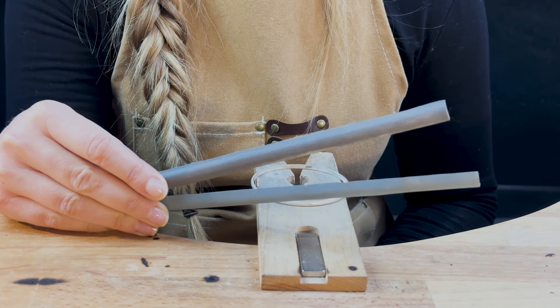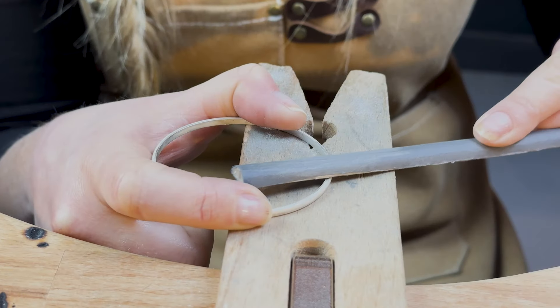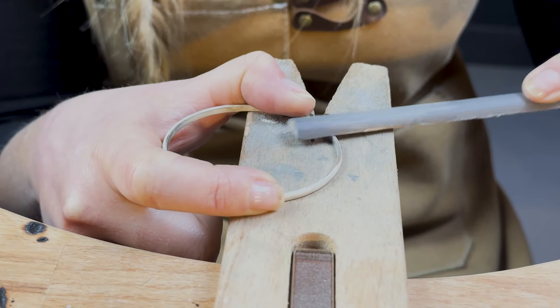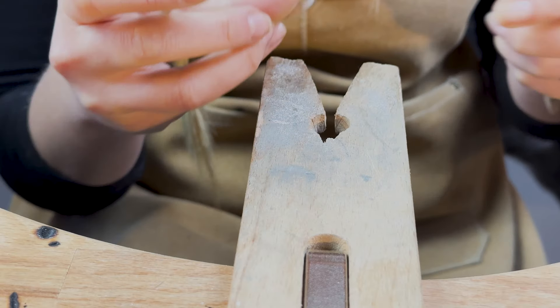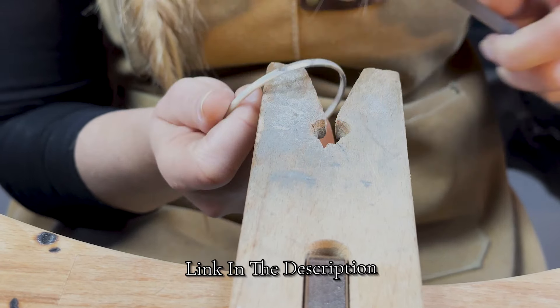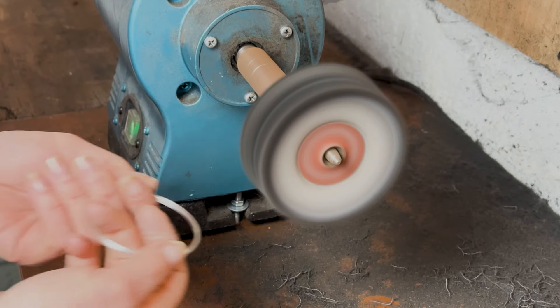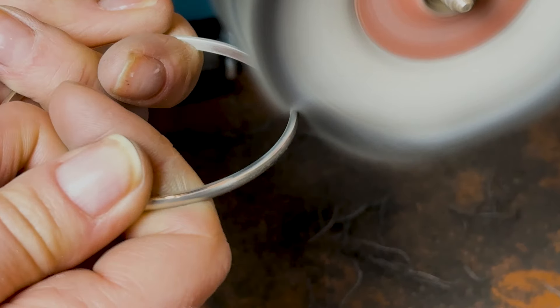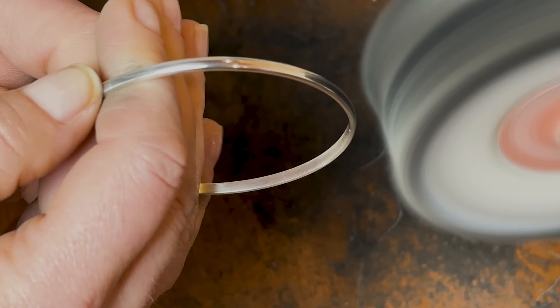To start, I'm using emery sticks to polish my bangle. These come in a range of grits from very coarse to very fine and can be bought ready made. You can also make these yourself pretty inexpensively with hardware store items — I've popped a link in the description. Polish the inside and outside of your bangle working your way up to the finest grit before taking your bangle over to the polishing motor. Polish the entire bangle using Tripoli and then Rouge until all the scratches have disappeared and your bangle is shiny.